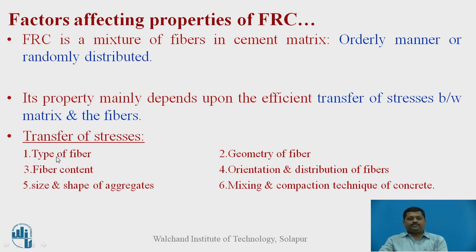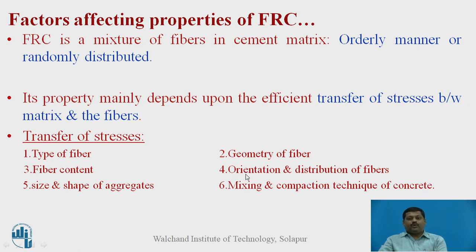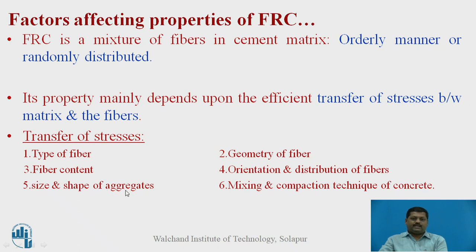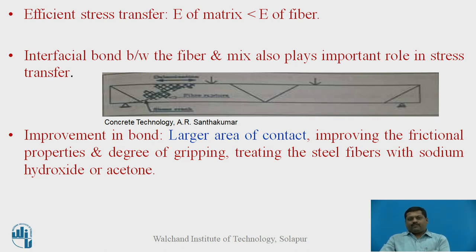Sub-factors affecting stress transfer include: (1) type of fiber; (2) geometry of fiber — whether plain, crimped, or hooked at the ends; (3) fiber content — the percentage of fibers used; (4) orientation and distribution of fibers — fibers oriented perpendicular to a crack arrest it more effectively; (5) size and shape of aggregate — which affects the arrangement of the cement matrix; and (6) mixing and compaction technique, which determines how bond develops between the cement matrix and the fibers.